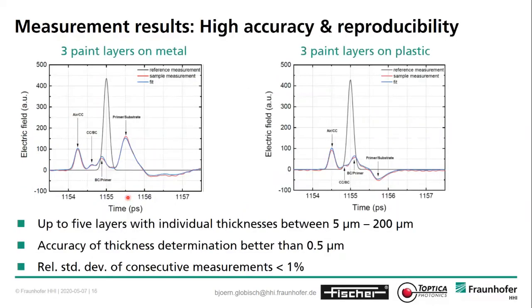And as I said, you can not only do this for a metal substrate, which is shown here on the left-hand side, this also works for a plastic substrate. The main difference is just the shape of the signal. Here for the metal, with a very high refractive index, you get the signal upside up, and from the plastic with a comparably low refractive index, this signal is turned. So in the end, you can use it for metal and plastics.